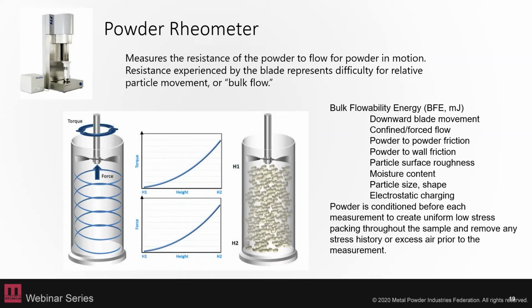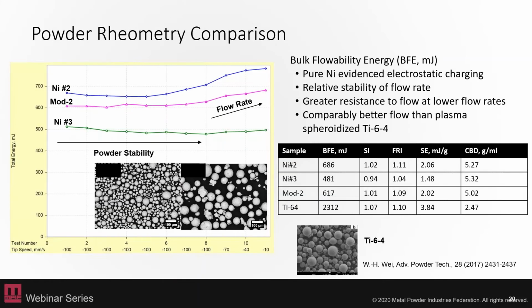energy, your powder-powder friction, your powder-wall friction, your surface roughness, your moisture content, different size and shape effects, as well as electrostatic charging, like we talked about with nickel powders, and potentially charging to a plastic material. So just as a comparison here, there are 2 different pure nickel powders, as well as a nickel-based superalloy, which is the Mod 2 pink curve there.